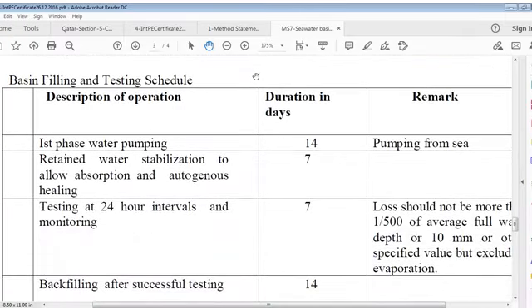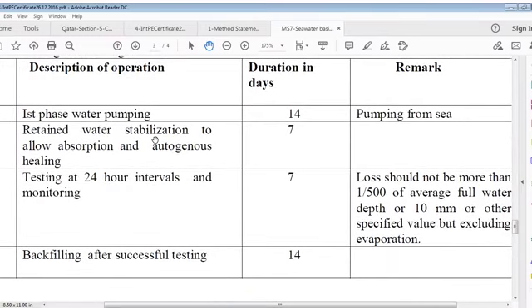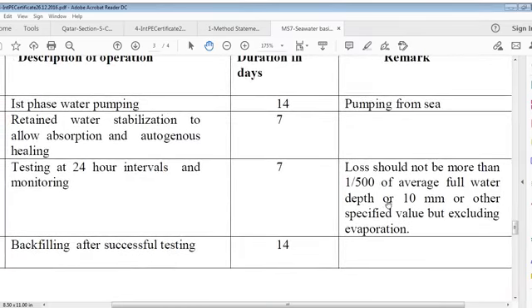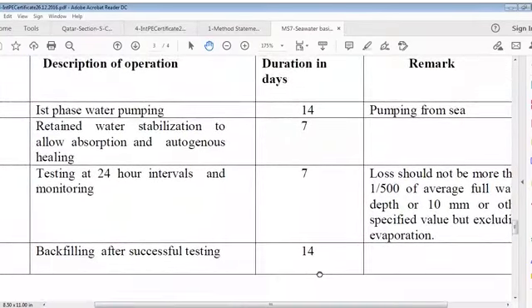Basin filling and testing schedule. First phase water pumping, 14 days duration, pumping from the sea. Then retained water stabilization to allow absorption and autogenous healing, 7 days. So 14 and 7, 21 days. 14 is for filling and stabilization period 7 days. Then testing at 24 hour intervals and monitoring, that is 7 days more. Loss should not be more than 1/500 of the average full water depth or 10 mm or other specified value, but excluding evaporation. Now backfilling after successful testing, 14 days. So 14 plus 7 plus 7 plus 14, this is 42 days.